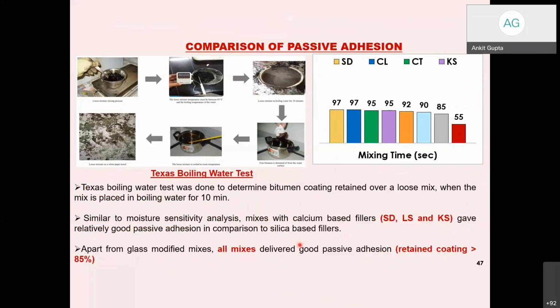Continuing with this, I think I'm only left with three or four more slides. The passive adhesion we tested with the Texas boiling water test. It is just the reverse of the adhesion part: we put the bitumen coated aggregates in boiling water, and then we see how much time it takes or how much of the coating is taken out from the boiling water. So how much of the aggregates remain coated? That is what we find out with the passive adhesion.